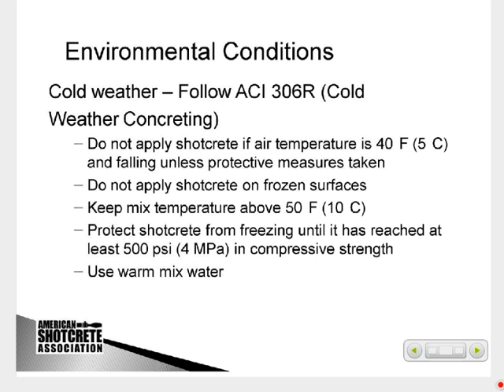In shotcrete, one entire surface is generally exposed because that's the side that we've applied the shotcrete from. Our rule of thumb is if the air temperature is 40 degrees and falling, you stop shotcreting, because shotcrete tends to have more cement than cast-in-place concrete. We find that we can reach that 500 psi level in shotcrete fairly easily if it's 40 degrees and going towards freezing, without freezing. If it is extreme conditions, you can certainly use warm mixed water. As with concrete, you don't put shotcrete on frozen surfaces, and you try to keep your mixed temperatures above 50 degrees.